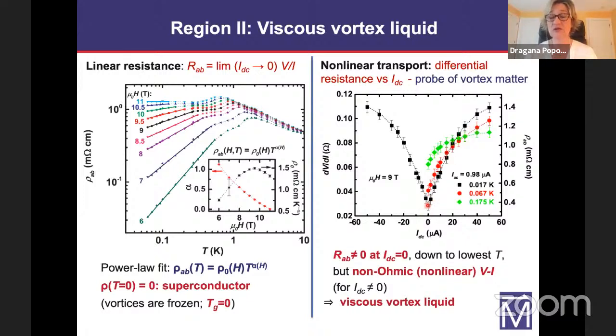So again, even though the linear resistance is finite in the limit of zero current, so these points correspond to these points here, we see that for all other currents, the resistance actually depends on the applied current, which is what one expects for vortices that are moving in the presence of disorder. So basically, as we reduce the temperature, the vortex liquid slows down and becomes more sluggish, more viscous. This is why the resistance drops, and eventually they freeze at zero temperature, so the material is a superconductor. And the existence of power laws is actually consistent with the proximity to this phase transition.